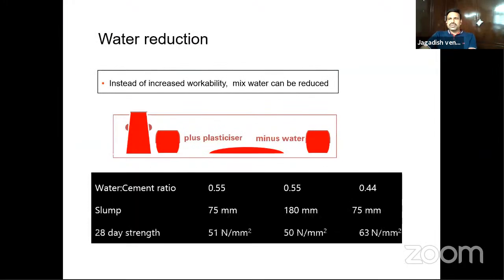So what we can do by adding the chemical admixture or the plasticizer, you can do two things. One is you can increase the slump without changing the water cement ratio. In the first case, you have 0.55 as the water cement ratio, 75 mm slump, and 51 MPa strength. Without changing the water cement ratio, you have added the chemical admixture so that the slump increased from 75 to 180 mm in the first case.